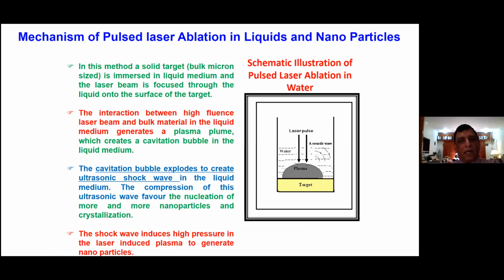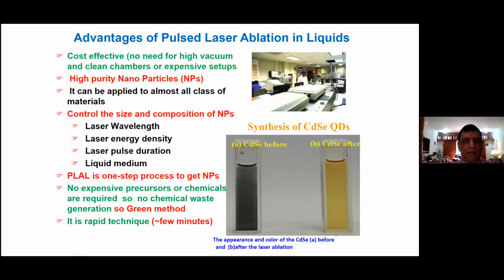We can create a cavitation bubble in there, and when the cavitation bubble explodes, it creates a shock wave, and that presses the bulk material, and it drives the nucleation process, as well as making the nanoparticle by that high pressure wave. The setup is just very simple. We have a laser, and by just controlling the laser parameters like laser wavelength, laser energy, laser pulse duration, and the liquid medium, or we add some surfactants if we like. But even without surfactants, we can control the size.